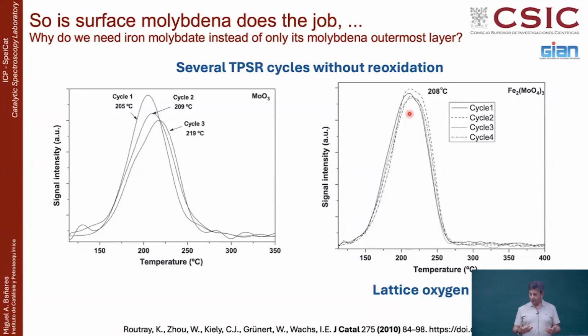In this reaction you are also feeding oxygen, but the migration of oxygen within the lattice, restoring the sites and everything, will be much more efficient on iron molybdate than on the molybdenum system. This shows only 3-4 cycles, but you're not going to be running forever without oxygen. You are feeding oxygen as well, but the whole system is much more dynamic. You have to be good at oxidizing, which both of them are, but also good at being regenerated and at oxygen mobility, because you have to recover. That's basically what this is showing.